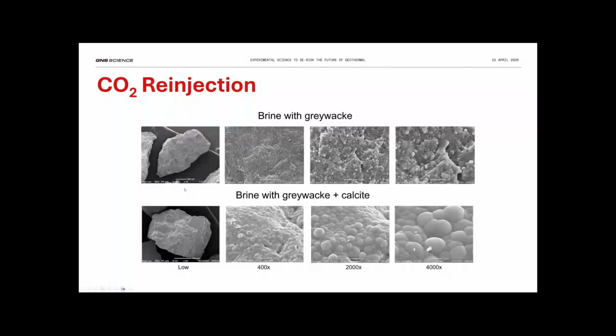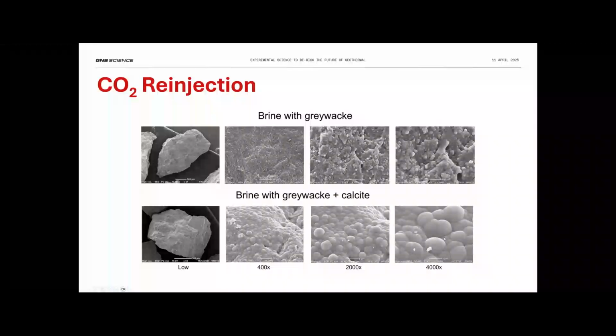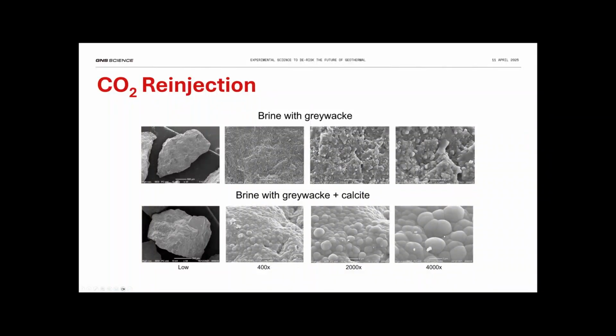And then when we add calcite to the rock, so we've actually added 2.5 weight percent of calcite to the same rock. So everything else is the same. And you can see there's dramatic silica scaling. And there's a loss of considerable amounts of silica. And the silica scale is quite thick when you compare it to the experiment without calcite.